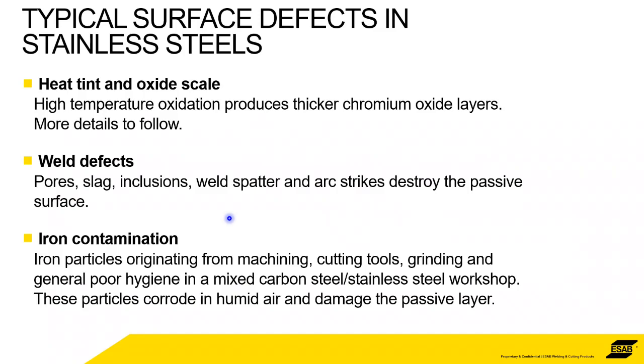So iron contaminations, things like from machining, especially grinding. If you're grinding and you leave grinding dust on the surface of stainless steel, then the moisture in the air will attack that and cause that to rust. So that will decay, and again that decay will take away the chromium oxide layer. So everything revolves around this chromium oxide layer.